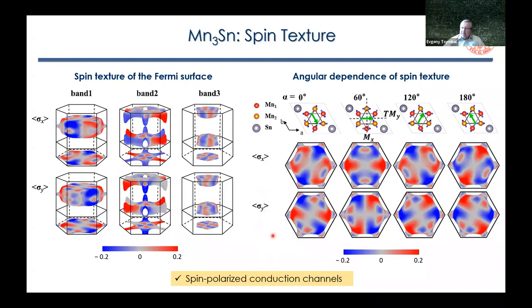So from this calculation, we can argue that if, for example, we can see a particular K point here, and assume that the spin at this K point has a specific orientation in the XY plane, then in the conditions where we have antiferromagnetic order, with the antiferromagnetic Néel vector being parallel, we should have the same orientation of the spin in the left and right electrodes as shown here.